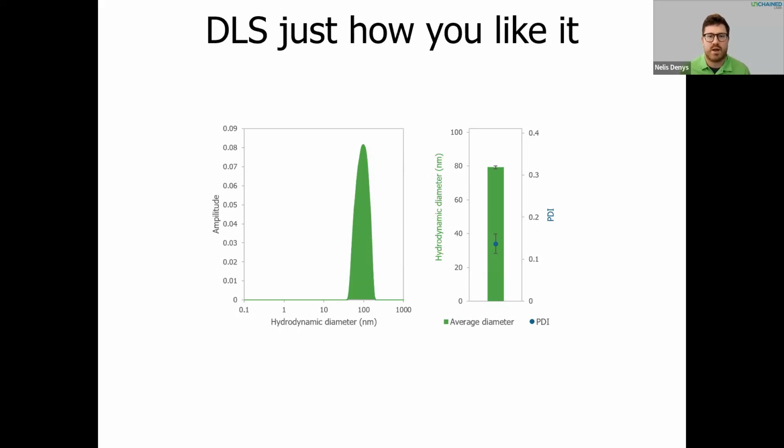And so here we're looking at mRNA LNPs with about 79 nanometers of hydrodynamic diameter, plus or minus 1%, and the PDI was around 0.14 plus or minus 0.02.